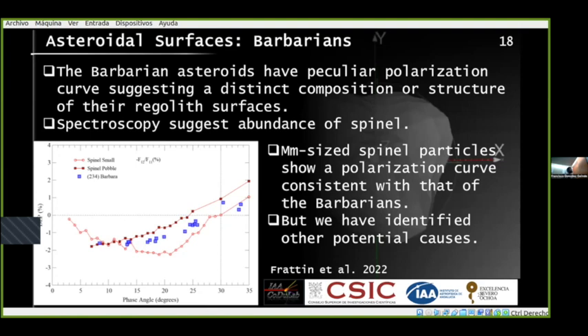And actually what you see is that when you take a large spinel pebble, a crystal of a few millimeters in diameter, in radius, you see a very similar polarimetric behavior, as opposed to the polarimetric behavior that you see with the powder. So we have the powder of spinel. It has a similar inversion angle, but it has a very well-defined minimum, and it goes up to zero towards a zero phase angle.